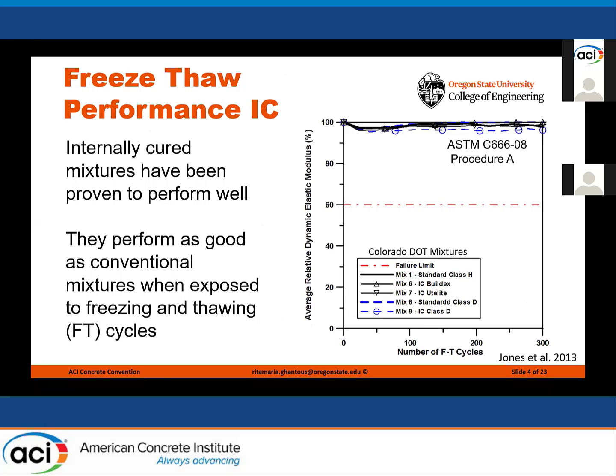It has also been proven that internal curing mixtures perform well under freezing and thawing environment. For instance, we present here the results of the study of Jones et al. in 2013. So in this study, the internally cured samples were exposed to freeze-thaw cycles following ASTM C666, and they performed as well as conventional mixtures, as illustrated in this graph. So in this graph, we can see on the y-axis the average relative dynamic elastic modulus, and on the x-axis the number of freezing and thawing cycles.